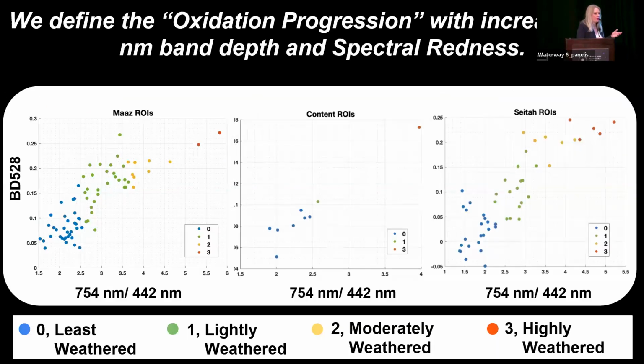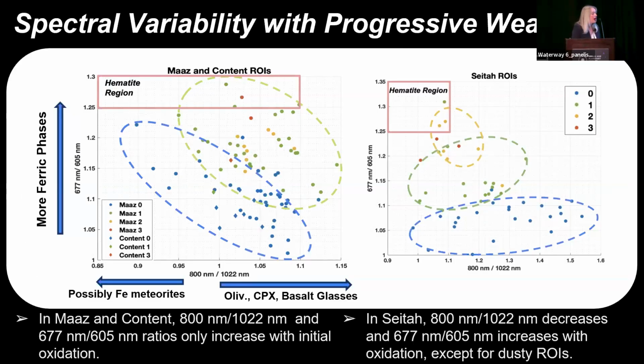So using this same ratio, we split the range of values for Maaz, Content, and Seitah into 4 equally sized groups and assigned them a value from 0 to 3, where 0 is least weathered, 1 is lightly weathered, 2 is moderately weathered, and 3 is highly weathered. We then used these assignments to track their progression through a known parameter space that was used by Rice et al. to highlight the spectral differences between Maaz and Seitah. So we're really able to compare how those spectral features are related to changing the spectral features in other ways.